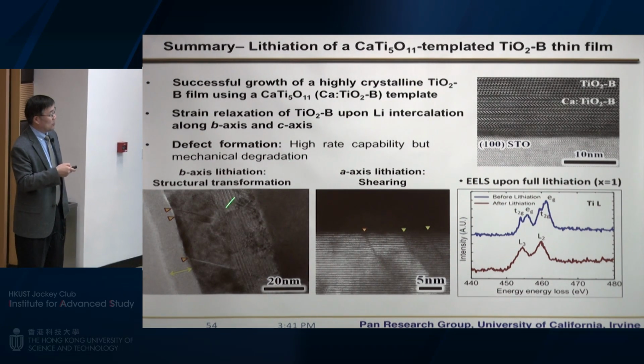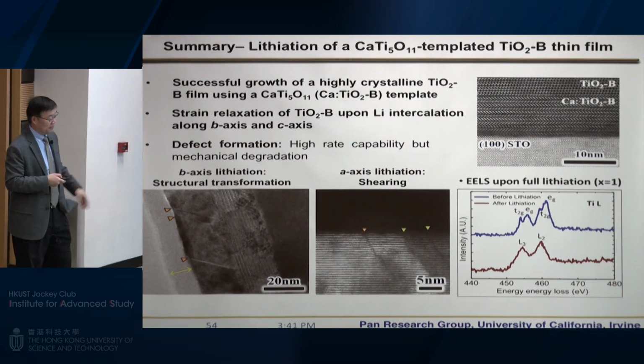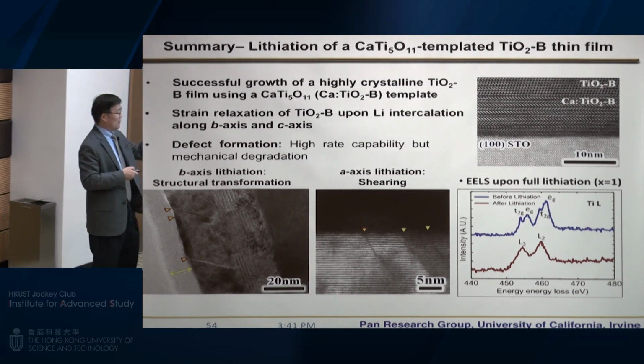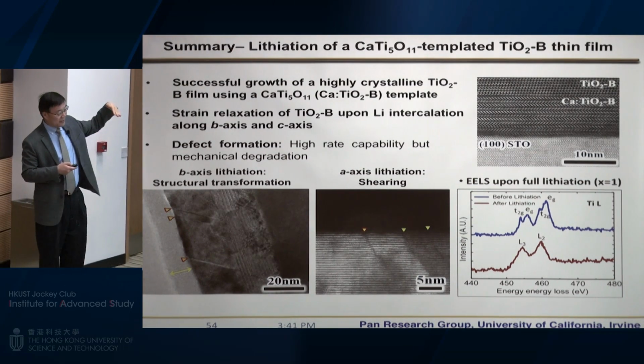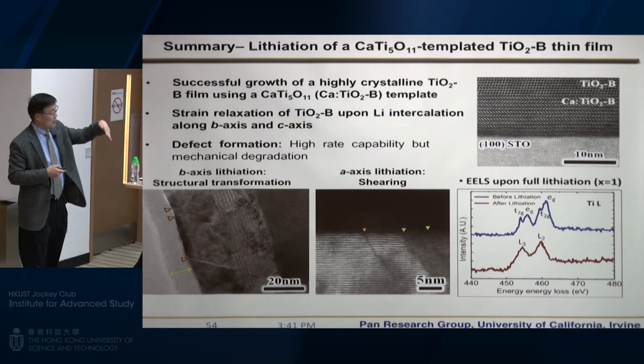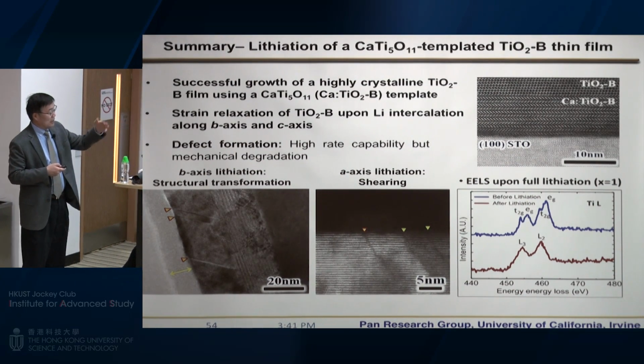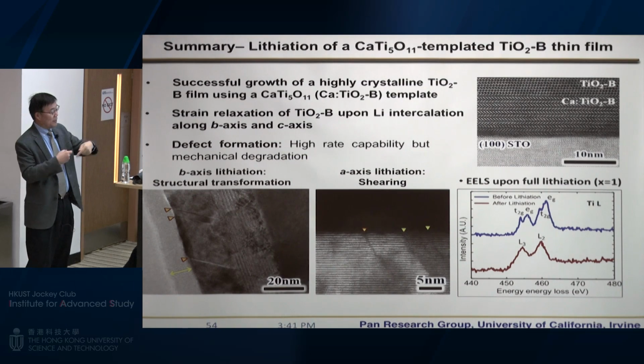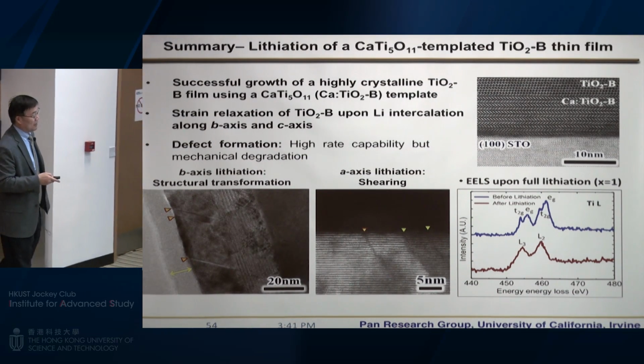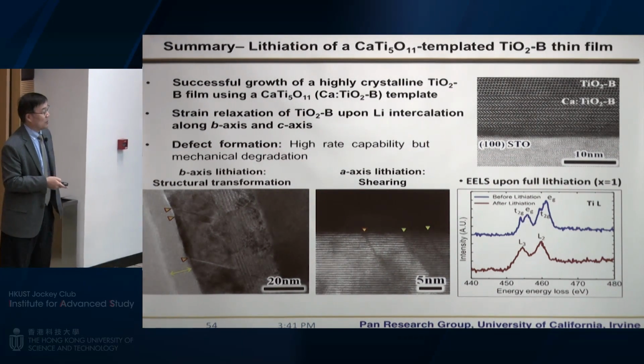And also with the in-situ TEM, we see there's two kind of defects formed during the lithium insertion. One is a very thin layer of anatase formed in the bronze B. Another is due to the strain relaxation, a lot of shear planes formed in the bronze B structure.